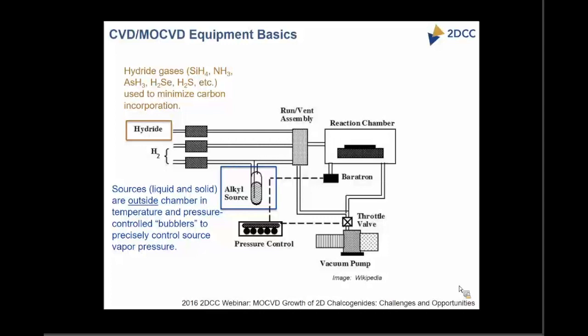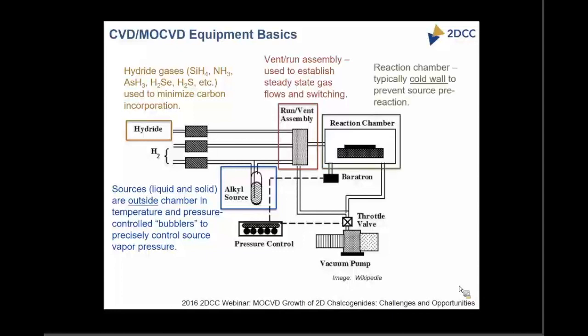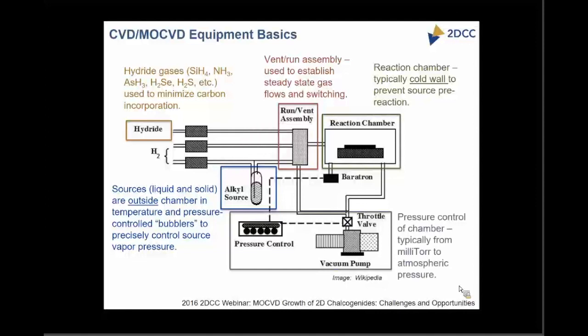Both the metal and the chalcogen precursors sit outside, with only the gas precursor entering the reaction chamber. For uniform growth, a run-vent assembly allows you to switch precursors between the reactor and the pump, forming stable gas flows during switching. The heart of the system is the reaction chamber — we typically use a cold wall system, where the substrate is heated specifically while the chamber walls are kept at a lower temperature to minimize gas-phase reactions and contamination. Pressure is controlled using a vacuum pump, throttle valve, and pressure gauge, from millitorr to atmospheric pressure.